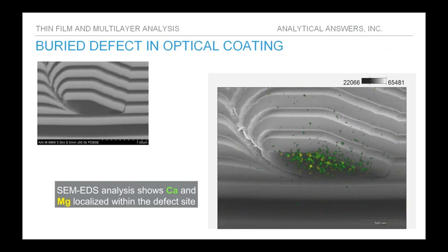An example of spectral imaging shows a buried defect in an optical coating. SEM EDX shows that calcium, shown in green, and magnesium are localized within the defect site. Neither of those materials is part of the film compositions used in this optical stack, implying a foreign contaminant species introduced very near the beginning of the deposition, or potentially insufficient surface cleaning before the deposition began, which led to the production of this particular defect.